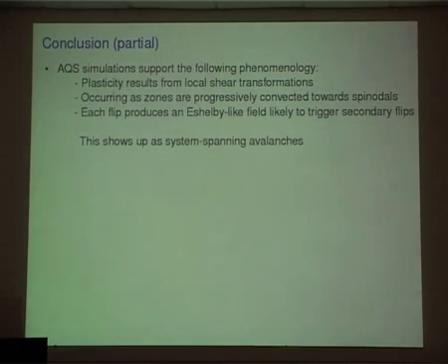And the second reason is that when you shear a system, you're progressively bringing these zones toward the thresholds. So you're creating a system where you have many, many soft regions very near instability. Because you have many regions which are near instability, as soon as one rearrangement emits these Eshelby stresses, it will modify the stress in a system which is very weak, and that will create an avalanche.